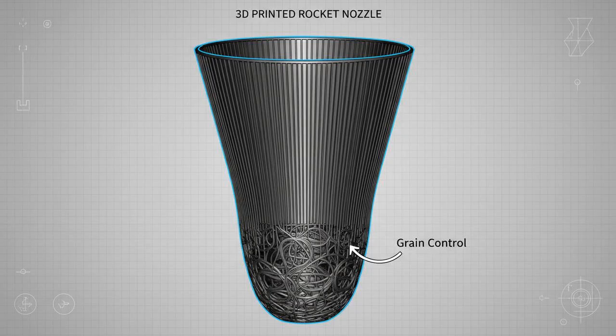In a cast turbine blade, engineers spend millions to grow a single crystal structure to eliminate grain boundaries, which are the weak points where breaks begin. In additive manufacturing, we are learning to print the grain structures we want. By manipulating the laser scan strategy, engineers can force grains to grow in specific directions. Imagine a rocket nozzle, printed with columnar grains running vertically to resist thermal stress, transitioning to random equiaxed grains in the mounting flange for better strength in all directions. It is total control. But there is a catch.